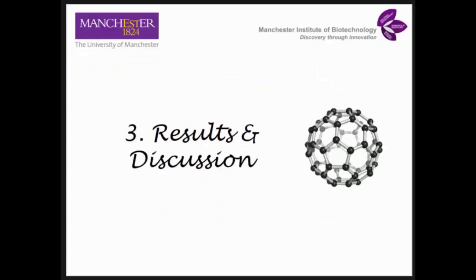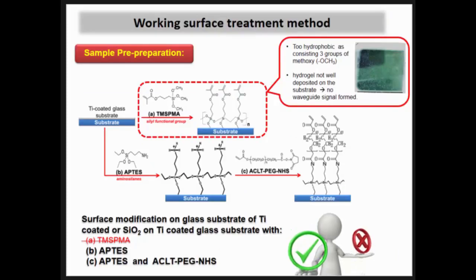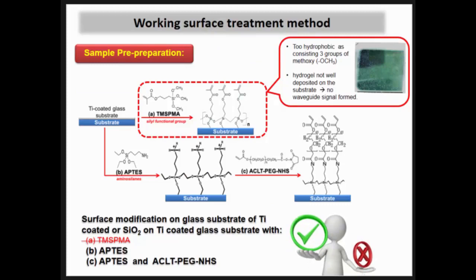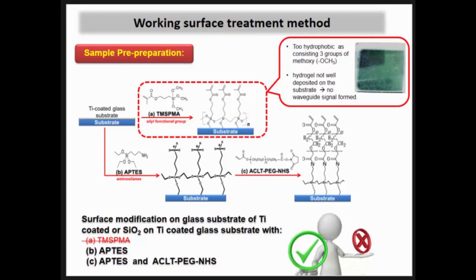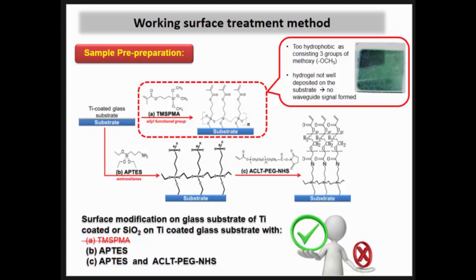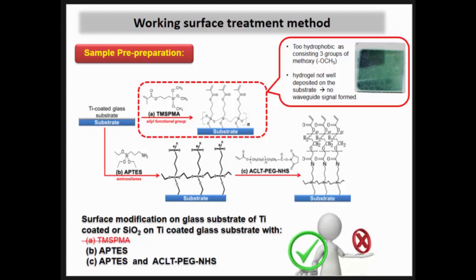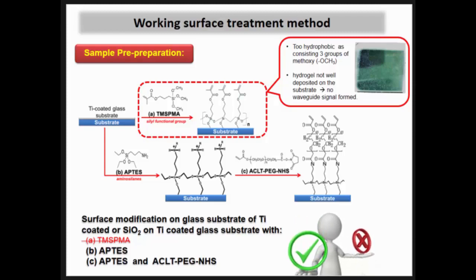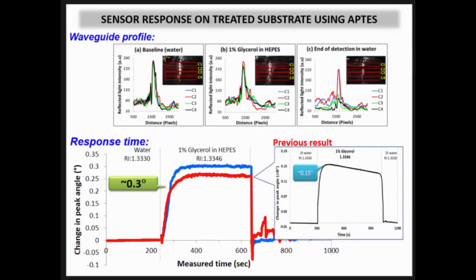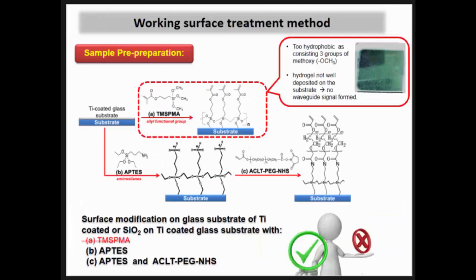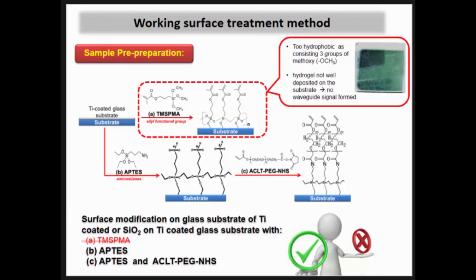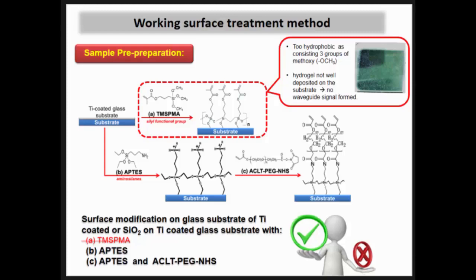So for results and discussion, for the first sequence, which is using TMS PMA as the chemical to treat the substrates, as you can see, I'm not sure if it is clear or not, but the hydrogel just forms small dots throughout the surface without any proper homogeneous layer. So it indicates that the surface became very hydrophobic. Actually, this is because TMS PMA consists of 3 methoxy groups, which made this substrate very hydrophobic. So it's not suitable for my case.